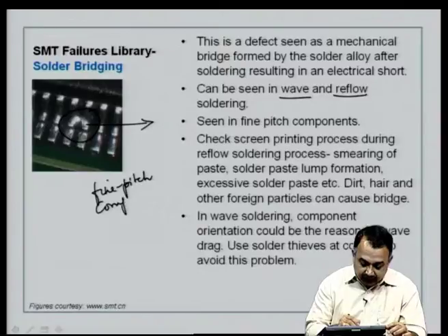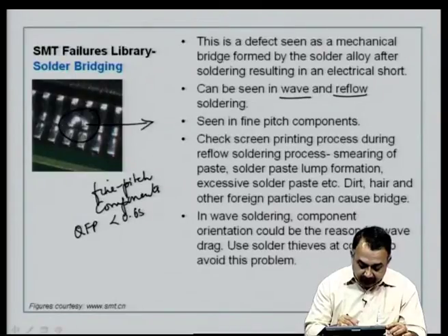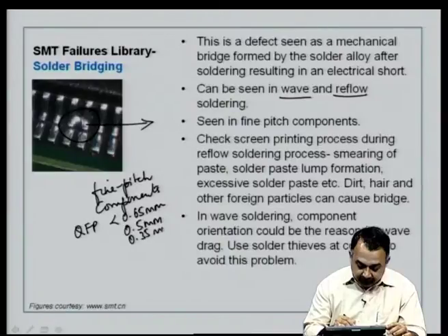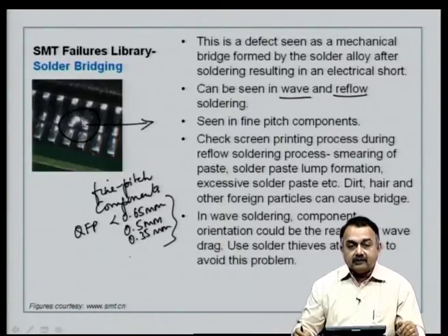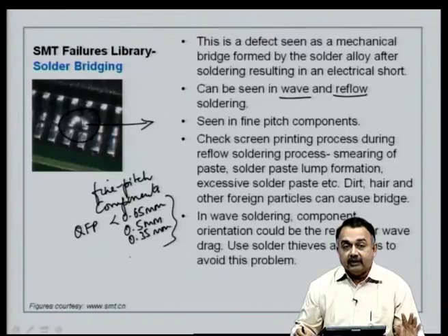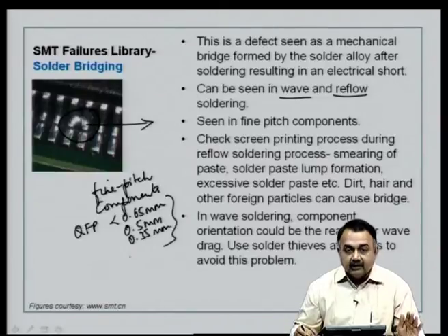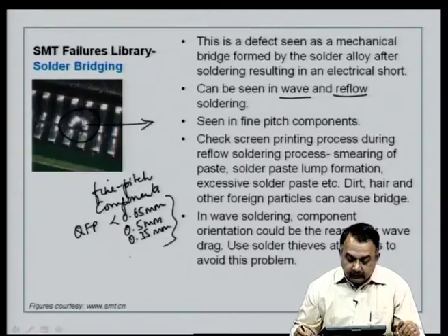So, if you are using QFPs, and if the pitch is less than 0.65 mm and very closely watch in 0.5, 0.35 mm, you will see there are chances for solder bridging. Therefore, your thermal profiling and again the quantum of solder paste that you are going to dispense has to be well measured. So, design considerations are clearly very important in manufacturing.